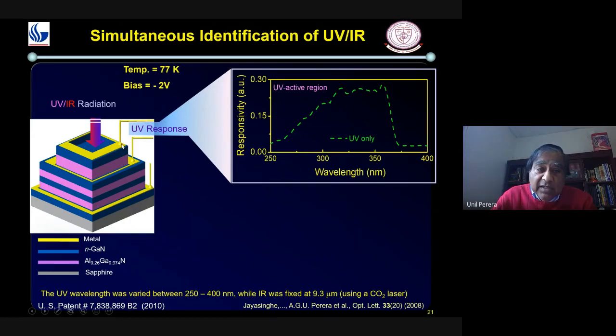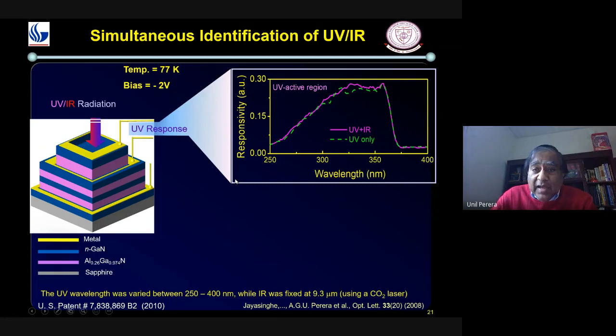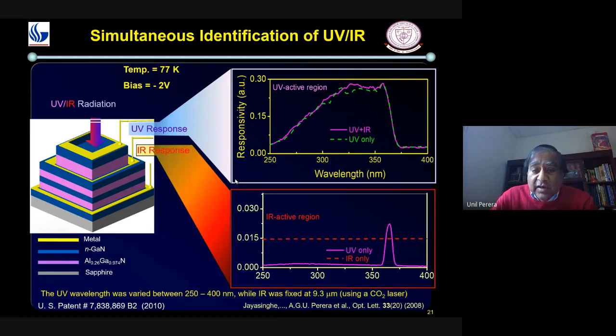We have modified our earlier diagram to have 3 terminals to detect this infrared and UV. So the top 2 gives you UV response, bottom 2 gives you the IR response. So this is the response for UV active region. And when both UV and IR are there, the signal is almost the same. So this is the infrared response. For infrared, ignore this axis because we use the CO2 laser, which is just 10 micron wavelength. So the red is the infrared active region, and when you just send UV, there is no infrared signal. So you see that light here, no signal, except this peak.